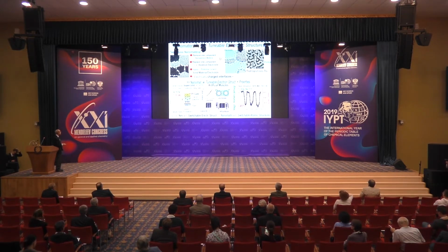I'll show you 3 examples. The one is the charge-induced superconductivity of strontium titanate. Strontium titanate in the pure form is an insulator. And what we did, we have a strontium titanate thin film, electrolyte, KClO4, and here a platinum gate, and we apply a voltage. And what we can see is when we apply a voltage and charge the strontium titanate highly, then the surface of the strontium titanate becomes a superconductor.